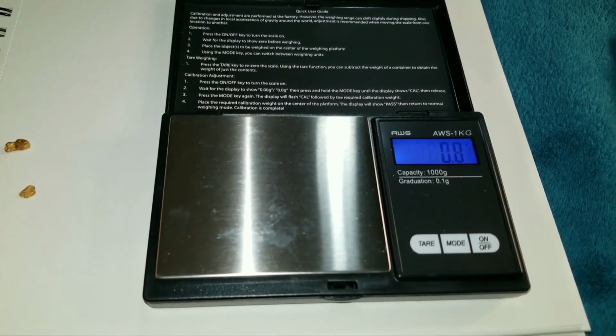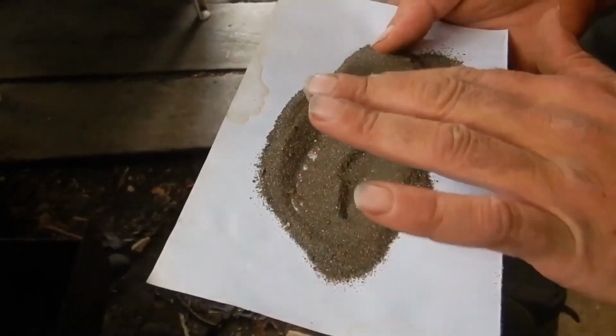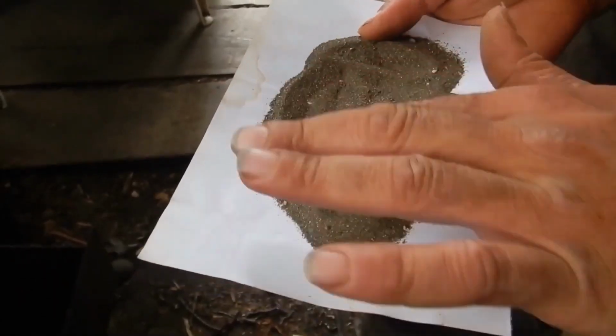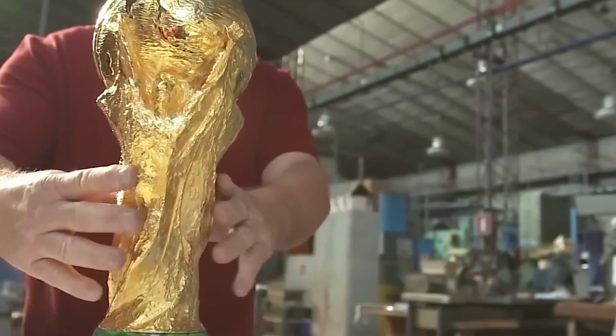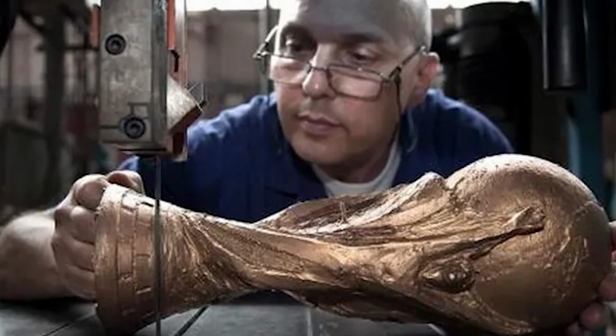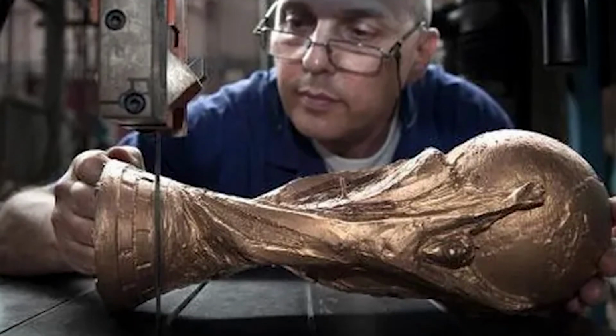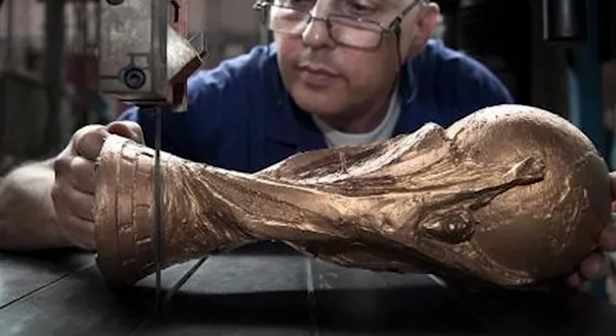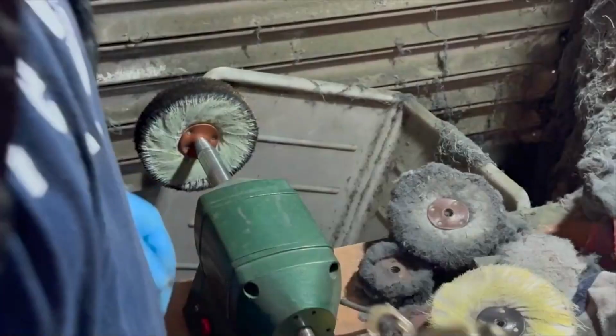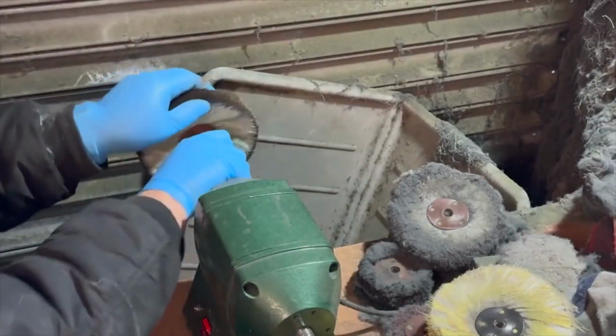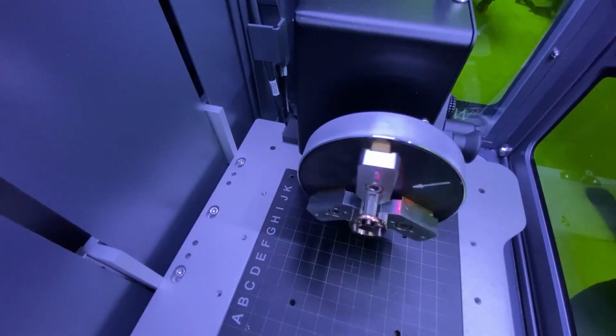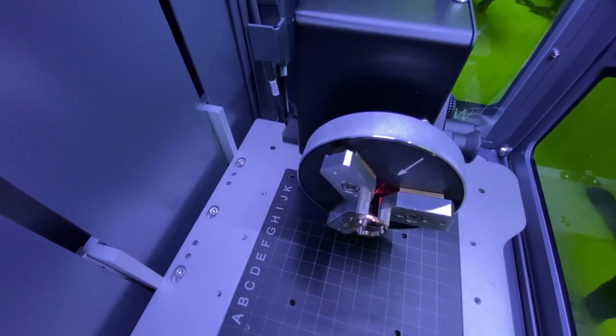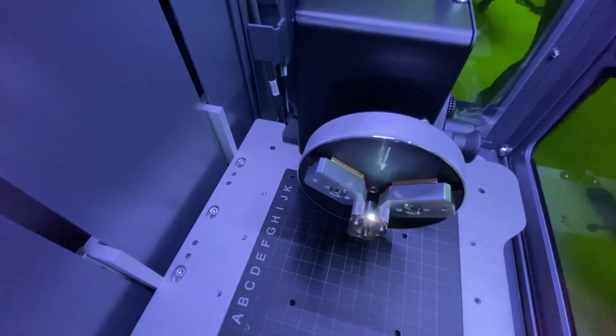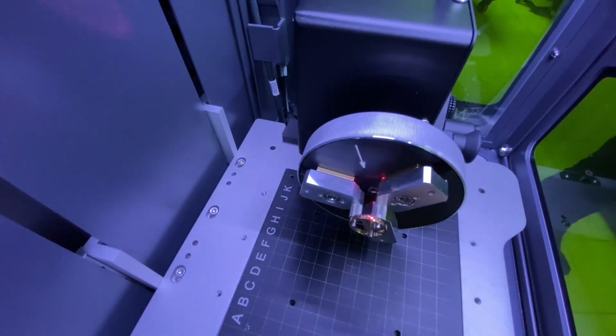With the channels removed, the inspection of the raw metal begins. Pores, shrinkage lines, small cracks, incomplete areas, or mold marks are sought. Some imperfections are superficial and disappear during filing. Others require repair with laser welding. This technique allows small amounts of gold to be added at precise points with highly localized heat. This fills a cavity without overheating the entire piece or deforming nearby areas.